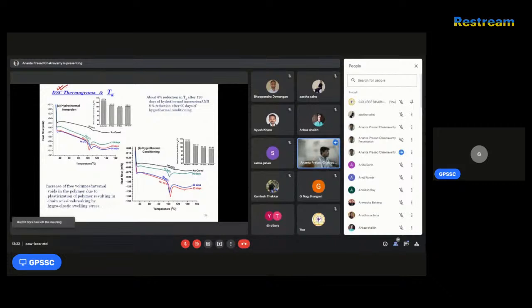Now you can also go for differential scanning calorimetry. My samples exposed to hygrothermal and hydrothermal conditions were scanned from 30 degrees to 150 degrees centigrade. After scanning, the first peak that comes for all is known as the transient state. Transient state means the time-dependent state. That means first it will absorb certain heat, and after a certain time it will provide a constant. Up to that time there will be a reduction in heat flow, which is known as the transient state.